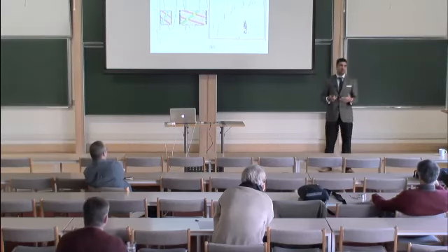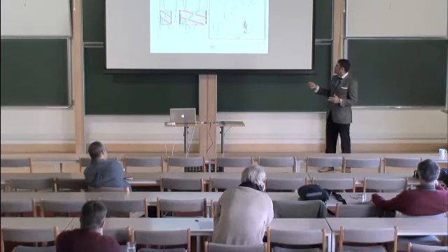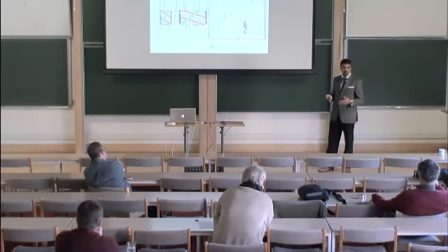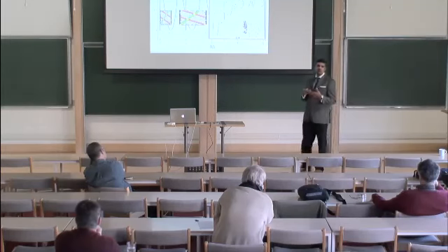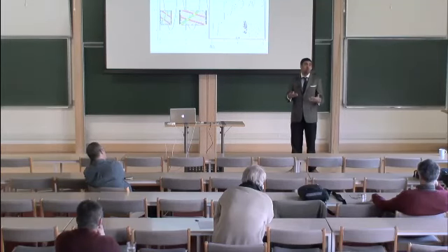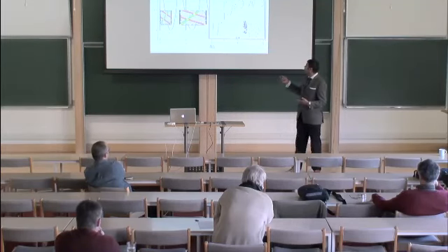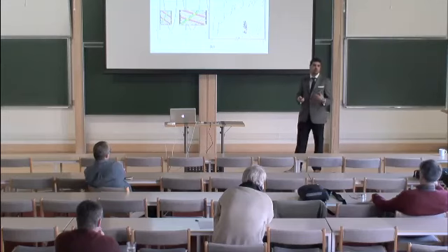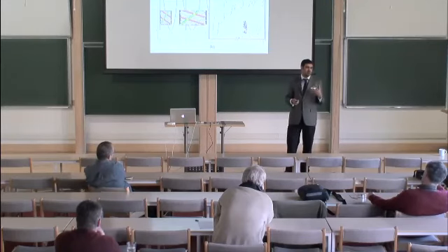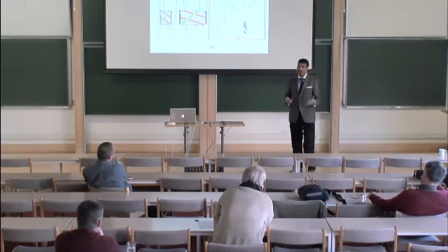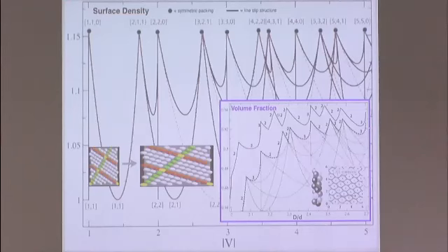Well, it's because of the very simple transformation that we use to account for the curvature of the cylinder. We can show that if we accounted for something more sophisticated, we could take into account these errors, but it would obfuscate the story I'm trying to tell you, which is that up until this point here, we can understand these sphere packings, 80% of them, entirely in terms of simple surface patterns and a simple curvature transformation. Okay?